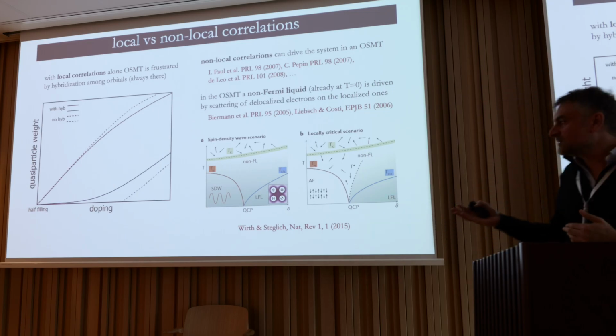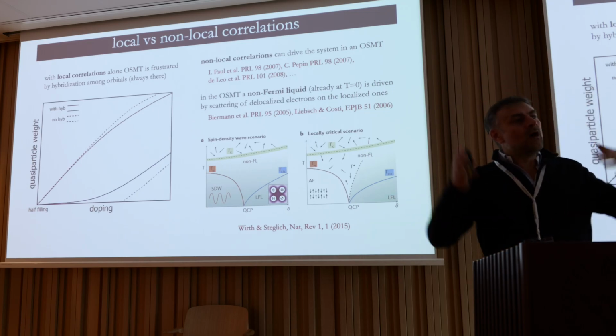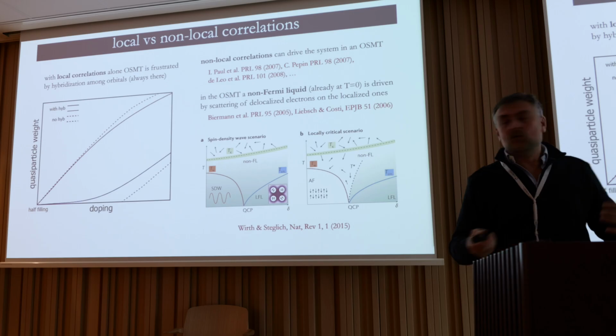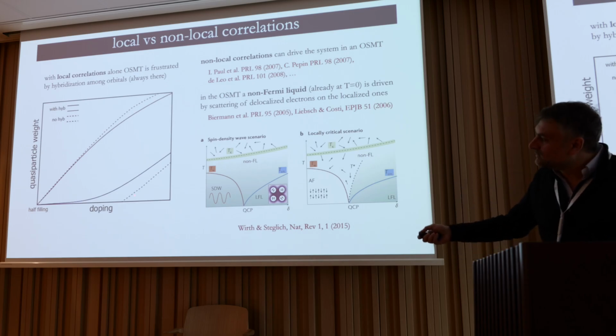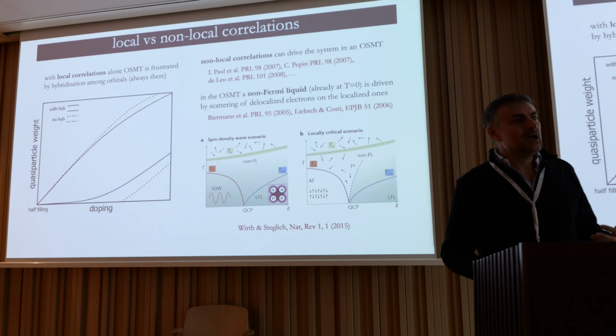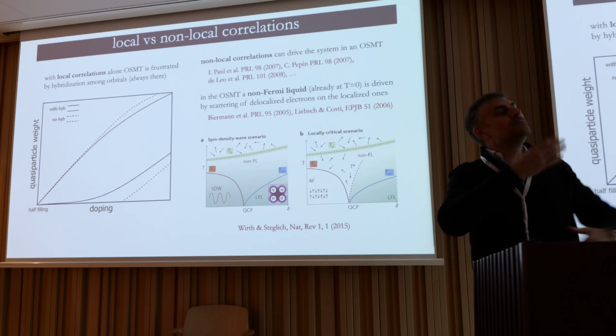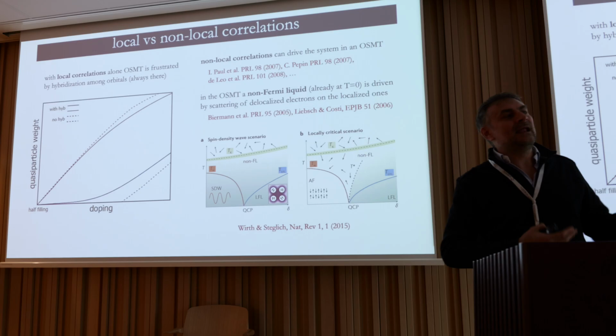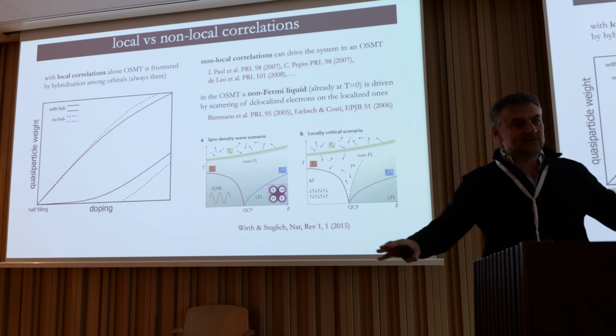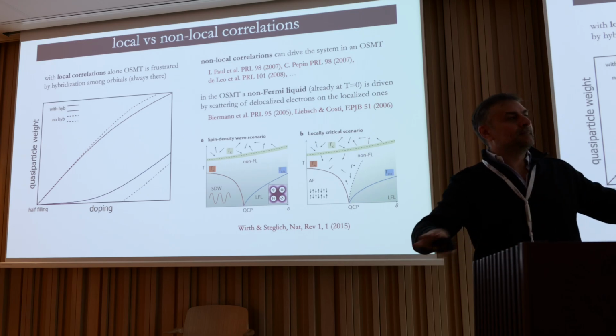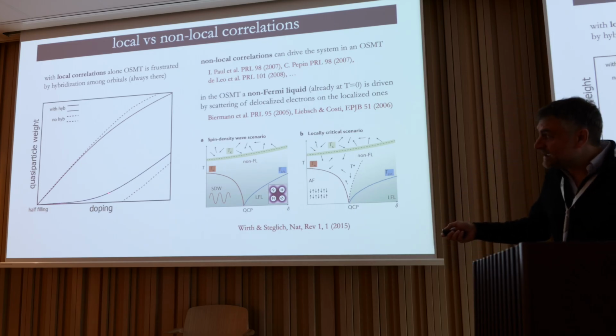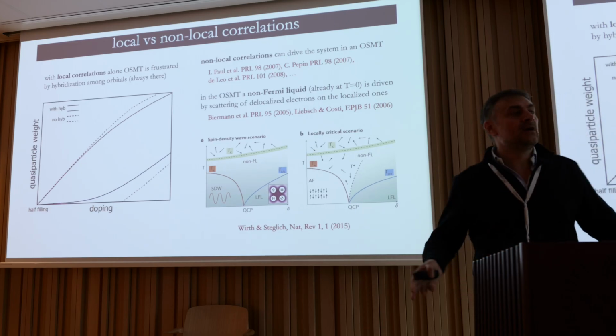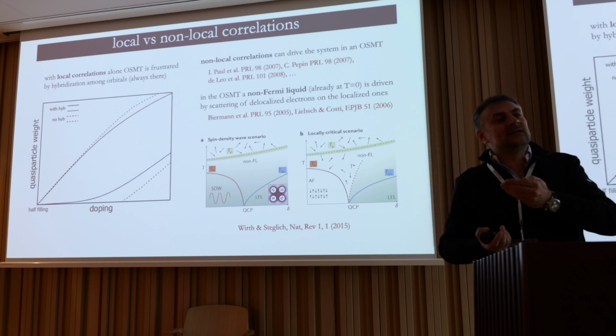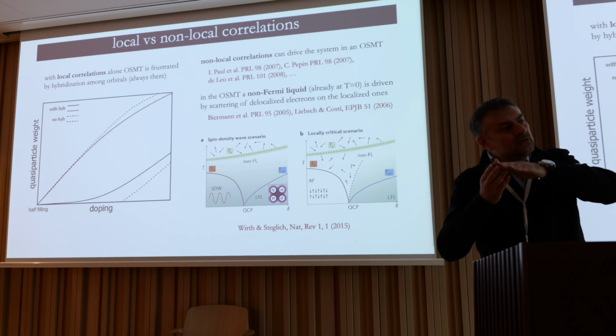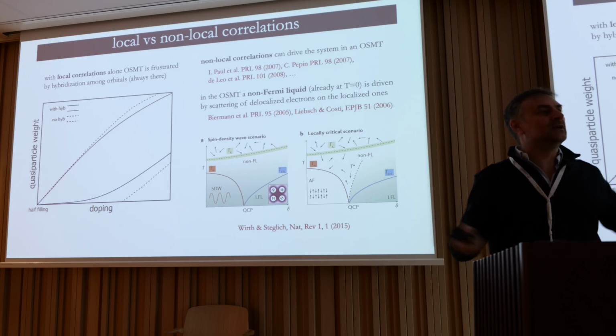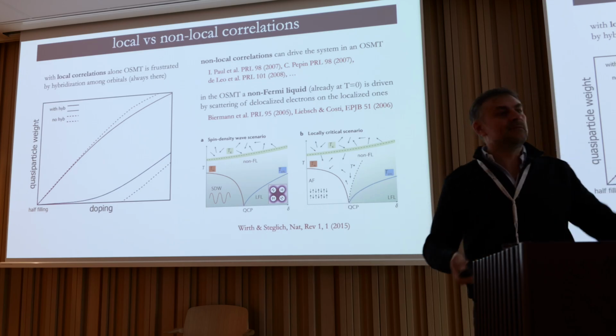Here you have this effect of the heavy electrons wanting to be insulating, so the system might want to do what's called an orbital selective Mott insulator, but it cannot, because it's still hybridized with the light electrons, and the light electrons prevent the heavy electrons from fully localizing. This is why we get an ample zone of parameters where electrons want to localize but cannot, so they become heavier and heavier, and you don't need fine tuning. You just easily find this heavy fermionic behavior.